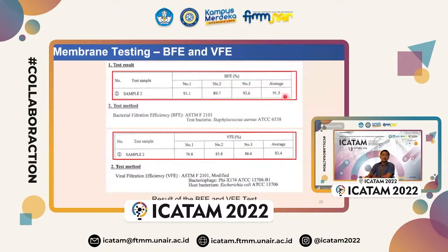So actually, the result came out quite good. We have a bacterial efficiency of 91.5%, and for the viral filtration efficiency, 83.4%. But this is just a preliminary experiment. We can still improve the performance of this membrane by modifying the technique.